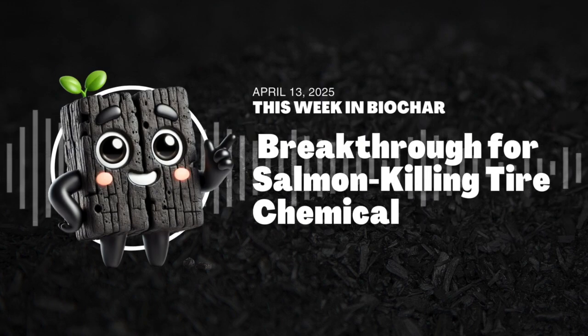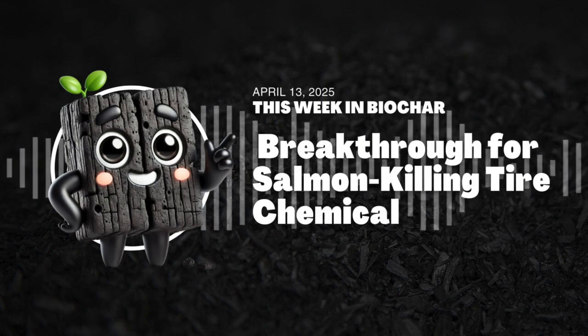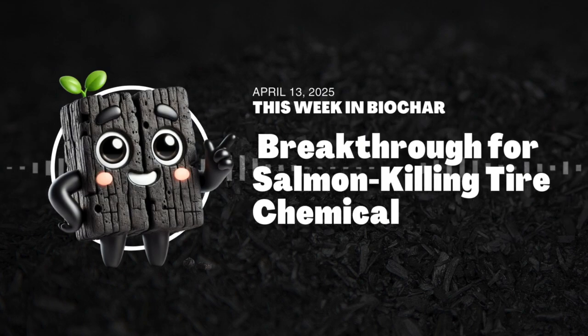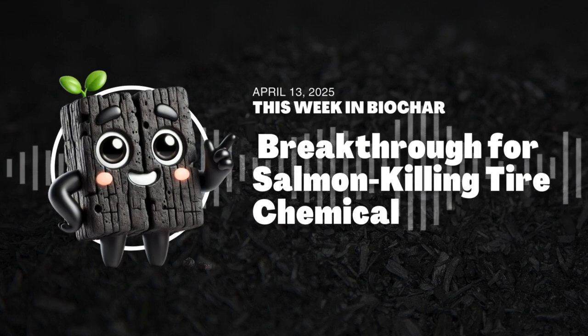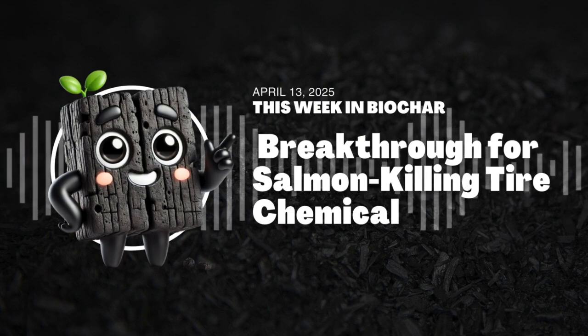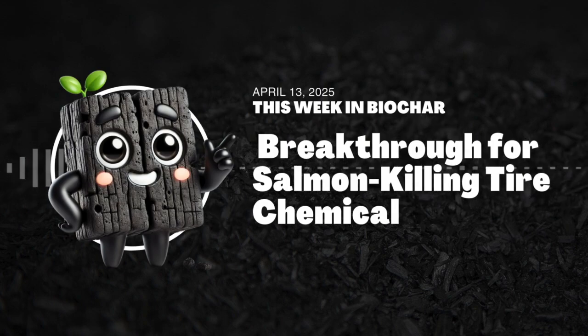Performance matters. And they managed this without hurting the carbon content. That stayed high. It did. Still around 90% carbon, which is great. You need that high carbon for stability in the soil, long-term carbon storage, all things that Biochar Today readers care about. Okay, but I saw there's a bit of a trade-off. The process uses up some of the carbon, about 20%. Yeah, about 20% of the biochar's carbon gets consumed in this reduction step.